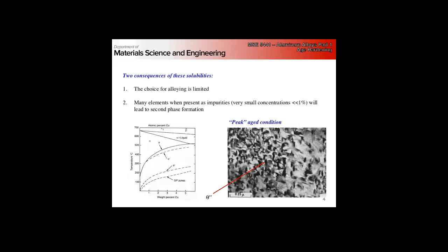So how come the easiest phases to precipitate also have the lowest solvus? Think about it from thermodynamics. A less stable phase would readily precipitate at a lower aging temperature. Well, it's the same reason as why we have the precipitation sequence.